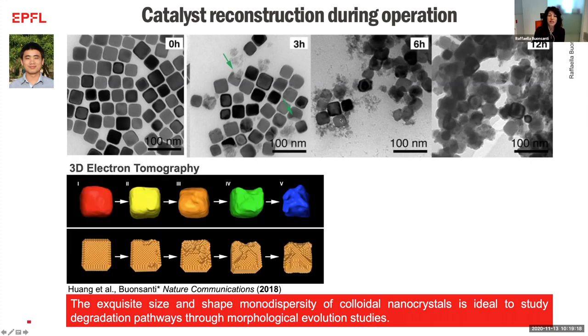What was also interesting for us is that when we perform three-dimensional electron tomography, we observe that these clusters detach really at the interface between the facet and the edges, which is really where we thought the active sites are. And it's actually a confirmation, if one believes that the more active a catalyst is, the faster it will degrade. This is also a confirmation that this is really where the reaction is happening.